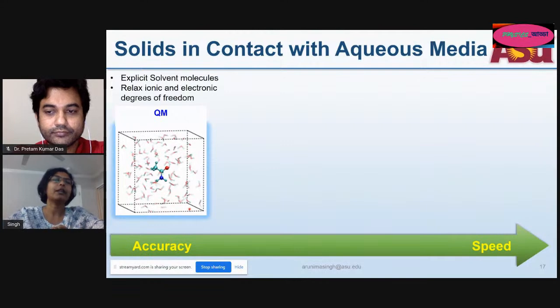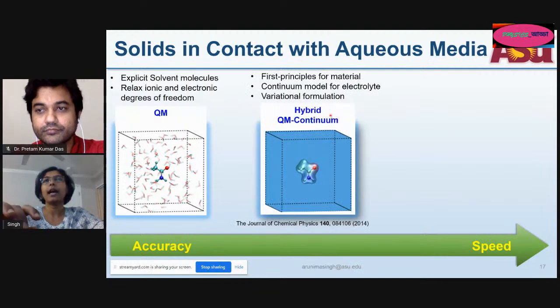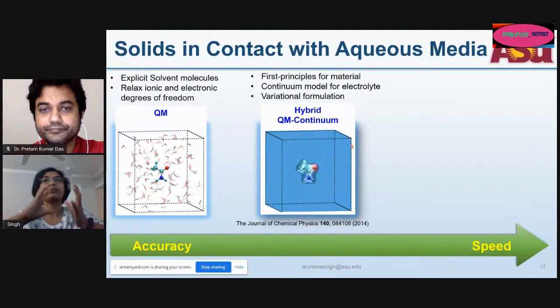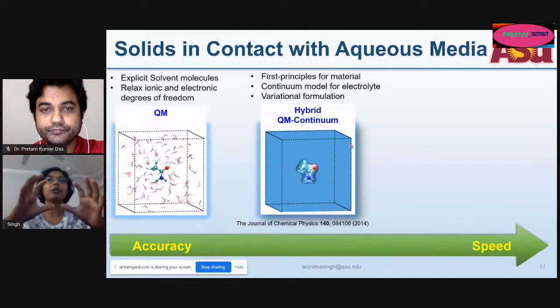Furthermore, you can't really look at the effects of pH and applied potential in this approach, especially for 11,000 materials, which we had for our system. The other approach is you can look at a hybrid quantum mechanical and continuum system where you use a continuum model for your electrolyte or solvent, and you use first principles for your material. Even though this is much cheaper than the quantum mechanical method, you still have to use ab initio simulations for your solid in consideration, which makes this process expensive. And again, you cannot look into the effect of pH.